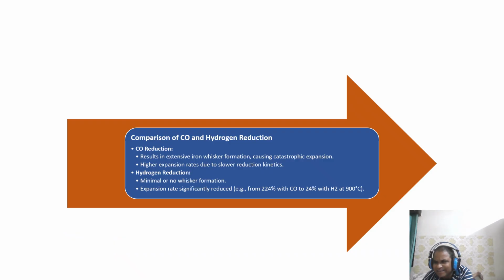Now, the question arises here, before going ahead, we must introspect. What is the reduction mechanism when a pellet comes across CO and hydrogen? Both reductions are a bit different. So let's break it down with CO. We can get catastrophic expansion up to 224%, thanks to slow reduction and crazy iron whisker growth. But hydrogen, it's a game changer. It slashes expansion to just 24% at 900 degrees centigrade with minimal whiskers. So hydrogen is the superhero of smoother steel production, we can say.